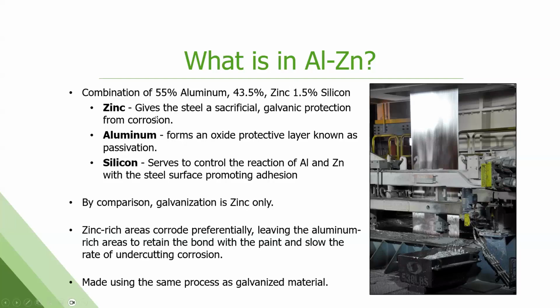Again, zinc is the sacrificial part. This is galvanic protection for corrosion. The aluminum forms an oxide protective layer known as passivation or a barrier coat. And that's why this product is going to last longer than galvanized. The zinc-rich areas corrode preferentially, leaving all that aluminum behind that not only is still protecting the steel, but if it's a painted product, you still have enough surface there for the paint to adhere to. If it's just zinc and that zinc wears off, the paint no longer has anything to stick to, and then you get paint bubbling and peeling off.